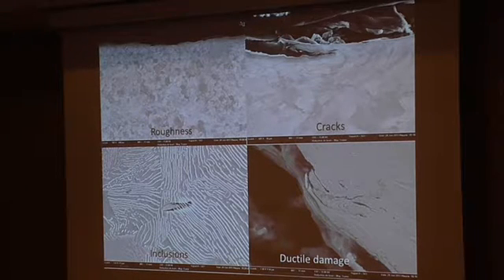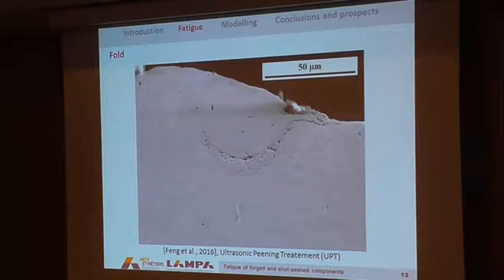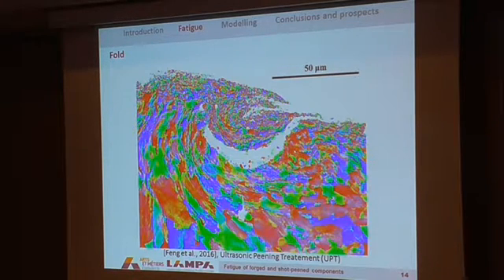What's very interesting here is that in some locations, due to the process, you can observe some cracks or fold, as you can see here. You clearly see what I mean by fold on this picture. You don't know exactly what this is here, and when you use an EBSD map, you clearly see that this is scale. This is scale incrusted into the material and potentially leading to a crack.